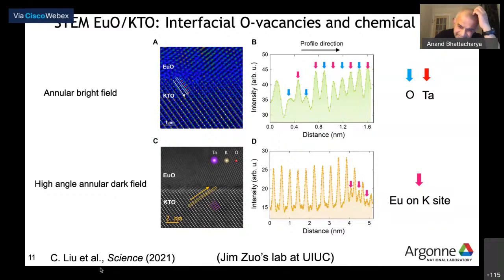In the bottom panel on the left is the high-Z sensitive technique. In this particular profile we are looking at an alternation of tantalum and potassium, tantalum, potassium. The big peaks are tantalum, and in the valleys there's potassium. Now, when you get close to the interface, where there was nothing before, essentially where the potassium is, much lighter than tantalum, you see these extra peaks. It turns out those are actually the europium atoms that have gotten into the sample.